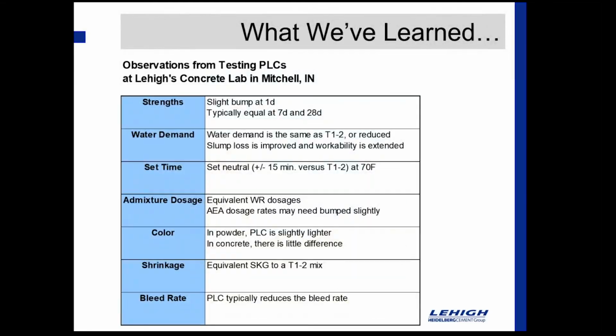And so I wanted to share some things that we've learned from some testing at our concrete lab in Mitchell, Indiana. These are just some generalities that we've discovered, some trends across different testing, different plants' production, as we've looked at this from 4 different Lehigh plants now. So in terms of strength, again, a slight bump at 1 day. Typically, those tend to moderate a bit at 7 and 28 days and equal more of the type 1 or the type 1-2.